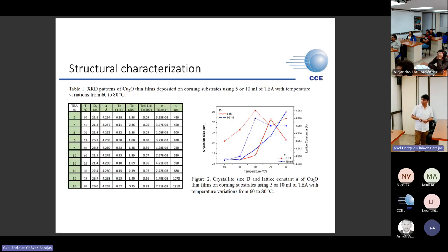These are the structural parameters of these films. Obviously, we observe an increase in the thickness in both cases, being more drastic when we use 10 milliliters of triethanolamine, which is related to having higher control because the copper is more complexed. So the copper ions are released more slowly to the solution, so it helps us to have greater control of the growth, allowing us to increase the thickness of the